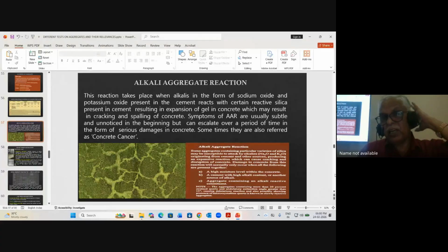Now coming to the alkali aggregate reaction, this is very important. Alkalis in the form of sodium oxide and potassium oxide present in cement react with certain reactive silica present in the aggregate, causing alkali aggregate reaction. This increases the volume, and you can see this type of cracks formed by alkali aggregate reaction - very critical.